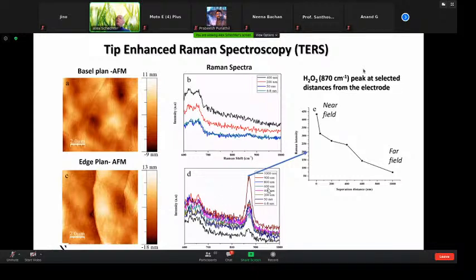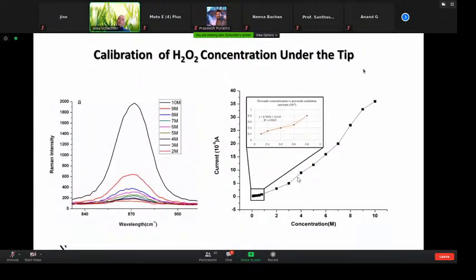We were able to calibrate it. We took different concentrations of solution of peroxide, and we were able to get a calibration curve just by looking at the increase of the height of the Raman peak at different concentrations. This is 10 molar down to 2 molar, and here is a fraction below 1 molar.